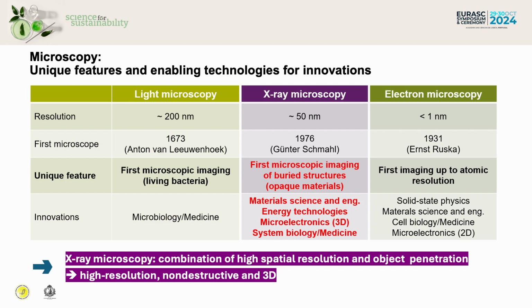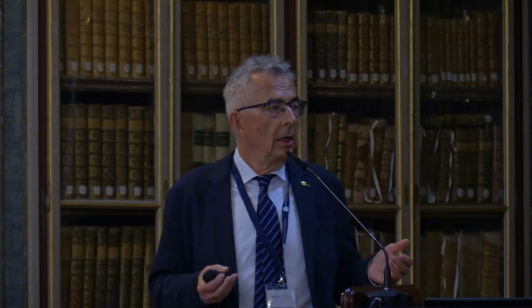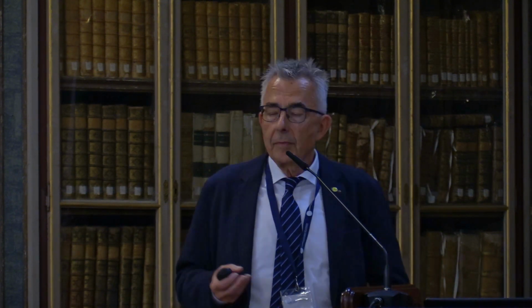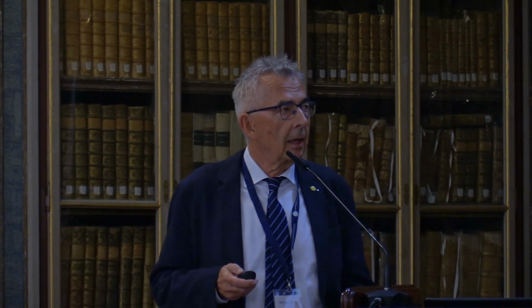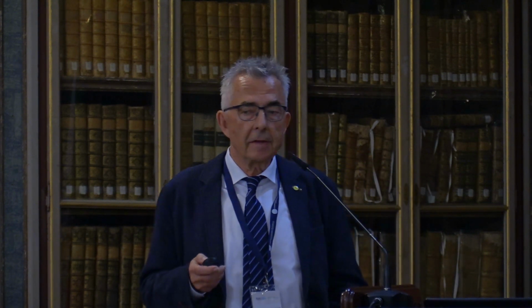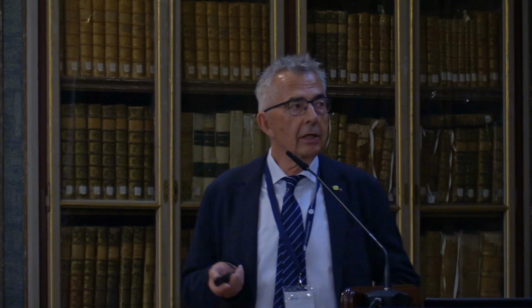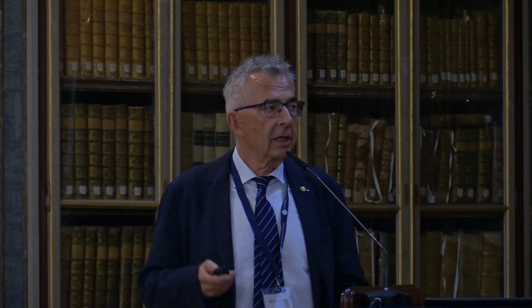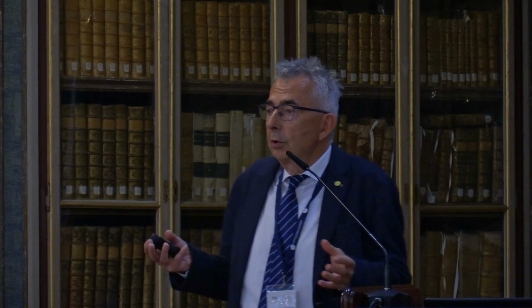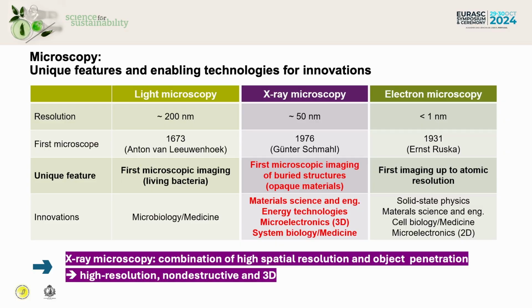Then we know electron microscopy down to atomic resolution. Without electron microscopy, it will be impossible to understand solid state physics, material science, and also 2D microelectronics. And here the first experiment was done in 1931 by Ernst Ruska. But in between is a very new field. It's X-ray microscopy with a resolution in the lab in the range of 50 nanometers. First experiment by Günter Schmahl from Göttingen at the synchrotron, 1976. But in the lab, we have the tools only for about 20 years now.